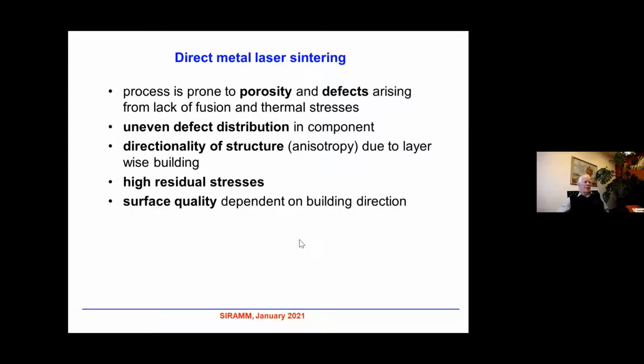The direct metal laser sintering brings problems which are mentioned here. The process is prone to porosity and defects which arise from lack of fusion, thermal stresses, scanning strategy, and so on. And this porosity and defects can strongly influence the fatigue properties. Not so much the tensile properties. However, from the point of view of fatigue, it may be very important.